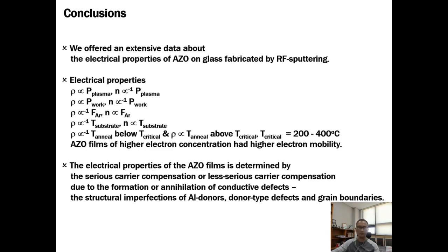Let me conclude this presentation. We offered extensive data about electrical properties of AZO thin films on glass substrates fabricated by RF sputtering. Electrical properties are like this. Electrical resistivity is proportional to plasma power and working pressure. But electrical resistivity is inversely proportional to argon flow rate and substrate temperature.